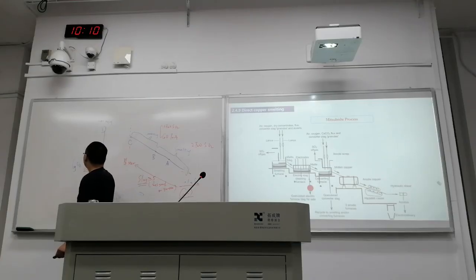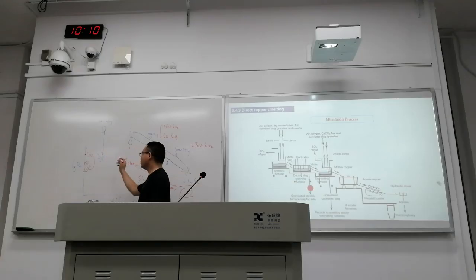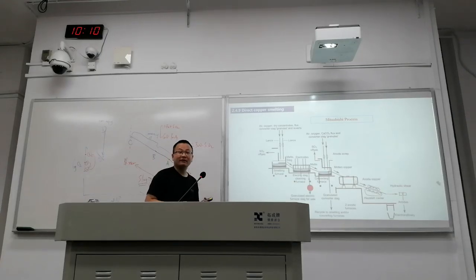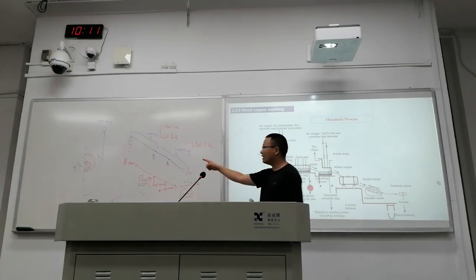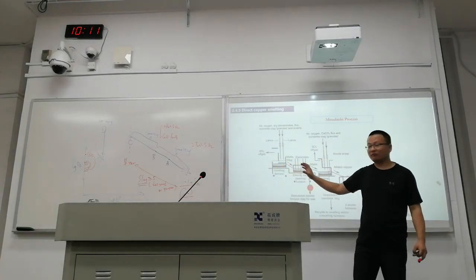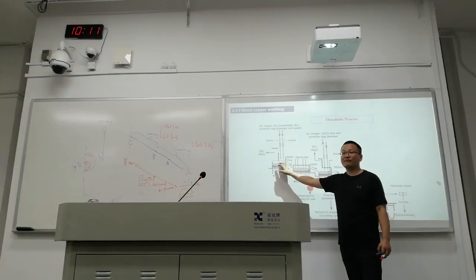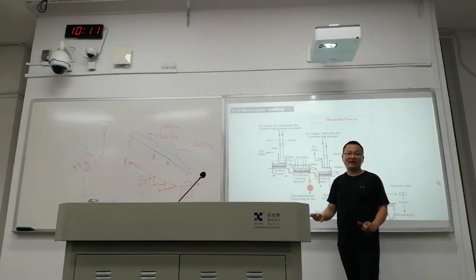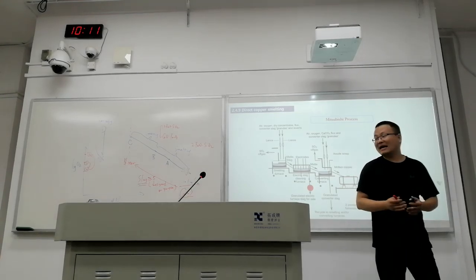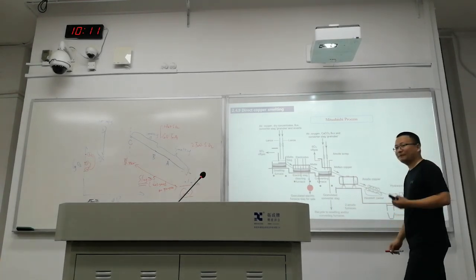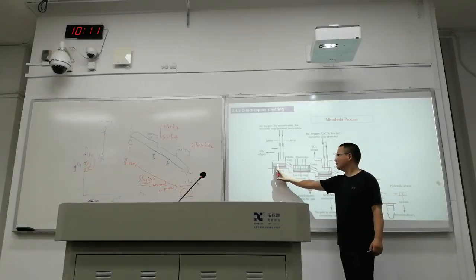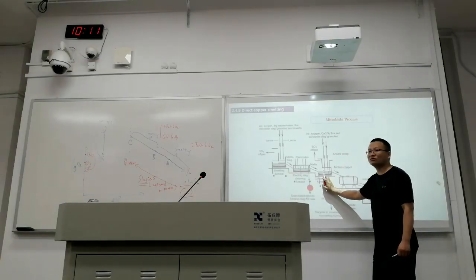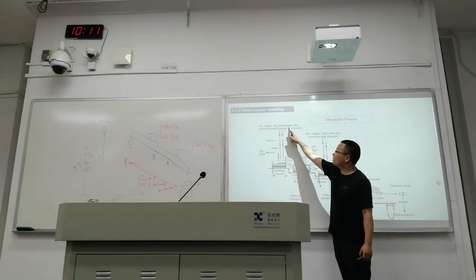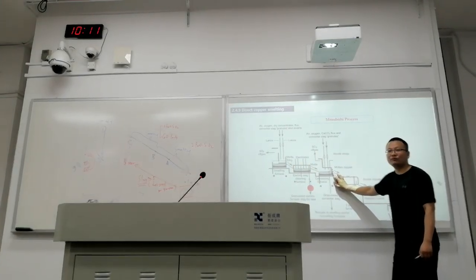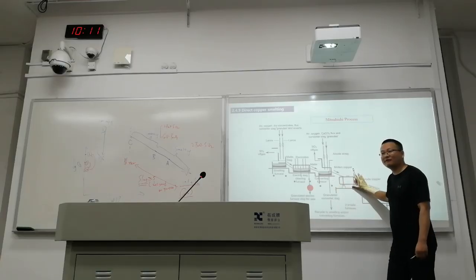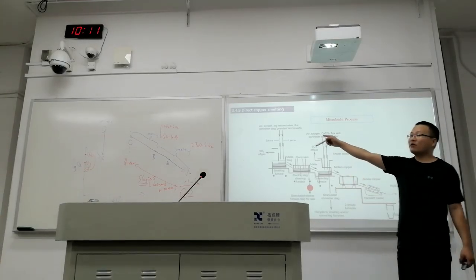So they are making such a circulation, trying to ensure the recovery rate of copper. So this is something you cannot achieve in one individual furnace. You have to make this kind of change. So the gas phase is homogeneous, so you are not doing that in one furnace. But physically, they have made this a reality. Concentrate adding, blister production. And this is the fourth furnace. So they are going for the fire refining.